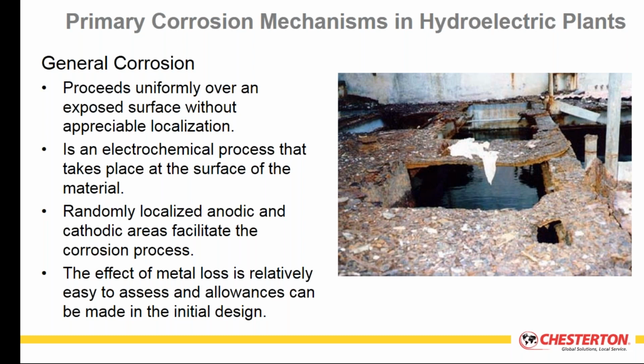The overall effect is the metal loss is relatively slow, and it's easy to assess lifetime. In design factors, if you know what the general corrosion rate is, you can design your structures with enough metal to absorb that loss over the lifetime expectancy of the equipment. But when we see general corrosion in hydroelectric facilities, it's mostly attributed to structural steel type applications.